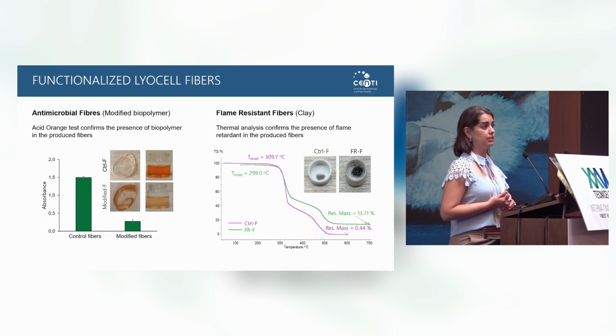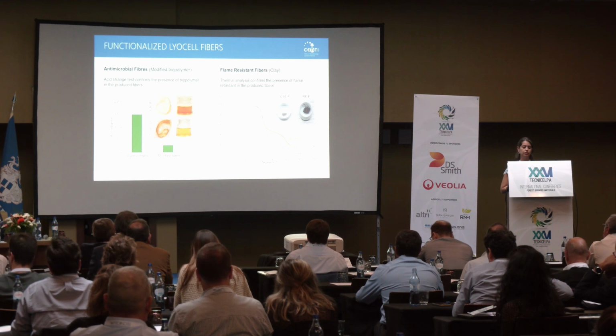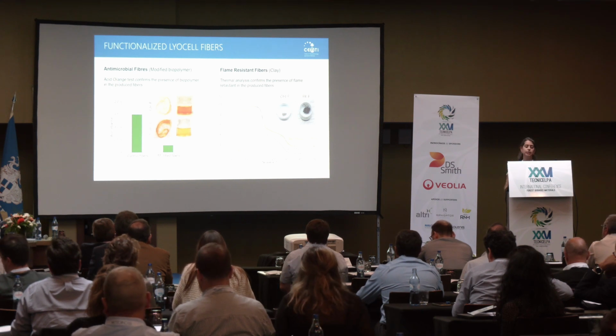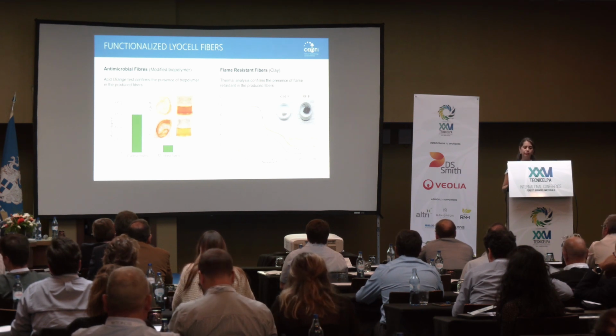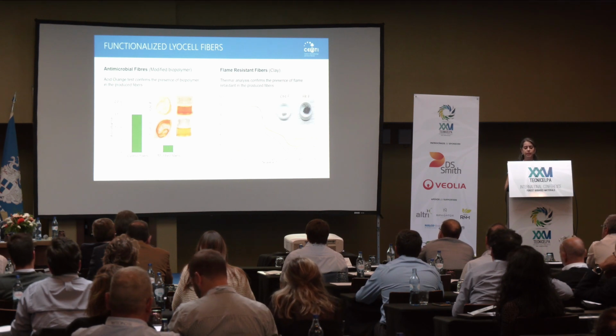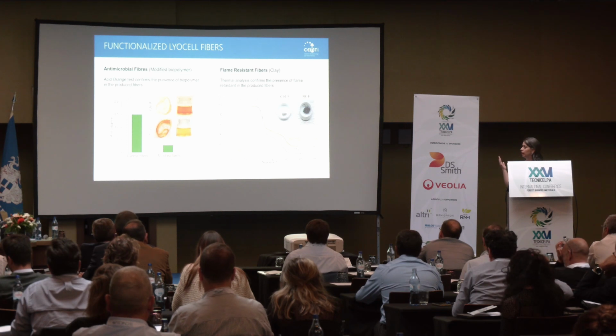For flame resistance, we also used thermogravimetric methods, where with 10% of the additive, we could see the typical behavior with the lowering of the decomposition temperature and increasing of the residue.